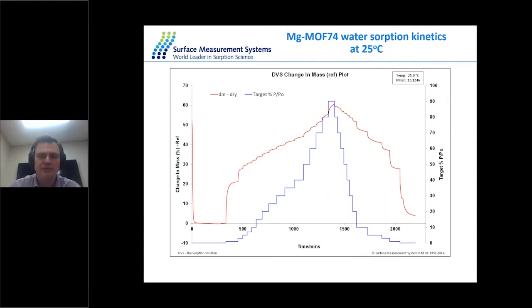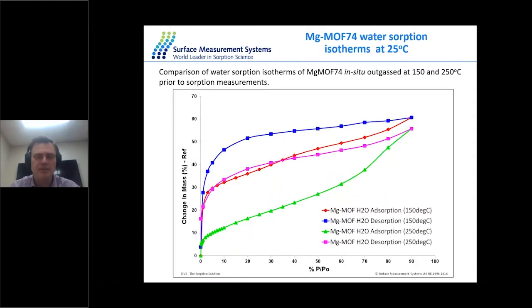Okay. So now, if you look at the desorption isotherms, what you're looking at here is magnesium Mof 74, and we outgas the material at 150 and 250 degrees. In each case, a fresh sample was used. That's very important.